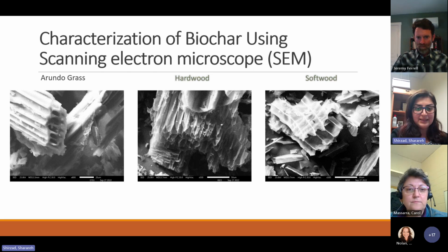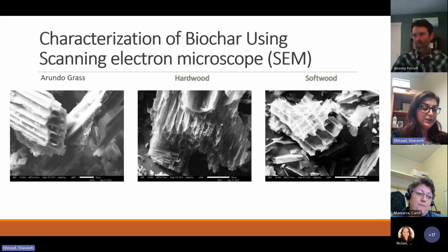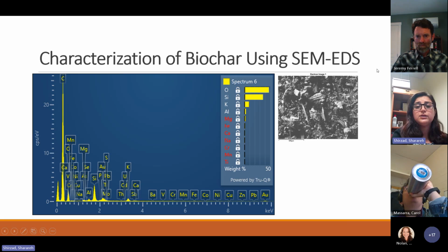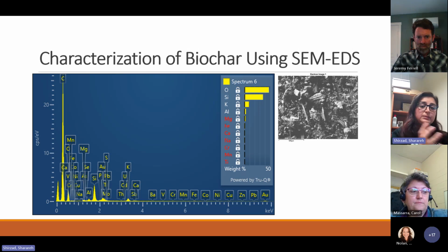And as you can see in this slide, we have SEM pictures for arundo grass, for hardwood and softwood. And again, you can see that these biochar samples are very porous materials, and that's why we think that it can help with internal curing of our concrete samples. And also another thing that we did, we characterized our biochar samples using SEM EDS. So we looked at the elements in our biochar samples to figure out the elemental structure of our biochar samples. And as we expected, we noticed a high content of carbon in our biochar samples.